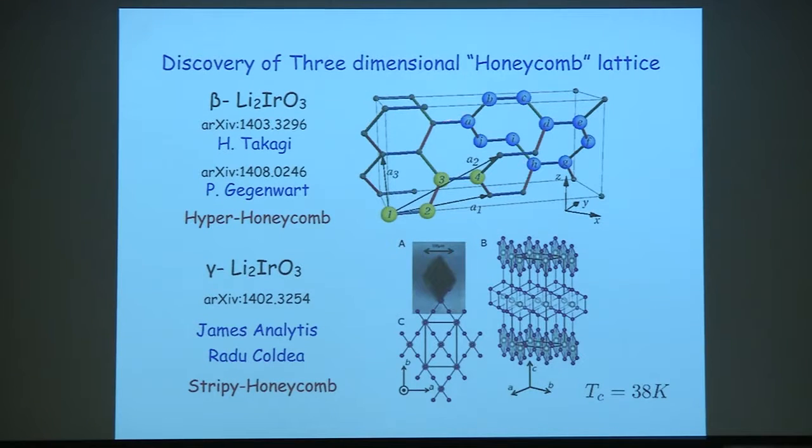In fact, if you have a 3-dimensional model, if you do 3-dimensional printing to get the lattice structure, and do the projection of it along a certain direction, it looks like a honeycomb lattice. But other than that, the smallest loop in this lattice is actually a 10-sided loop, not a 6-sided loop. Here, this one is closer to the 2D system in the sense that there are hexagons, but notice that the hexagonal plane here and the hexagonal plane here are rotated by 90 degrees. And you can alternate between these things, right? So this structure and that structure are different.